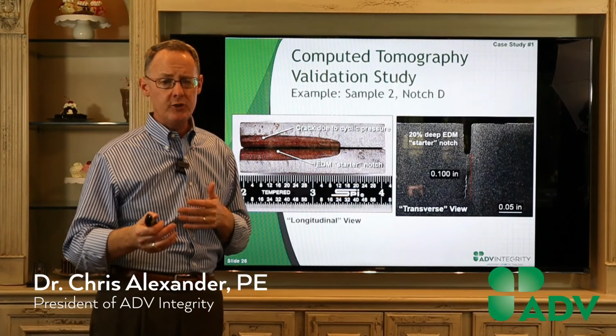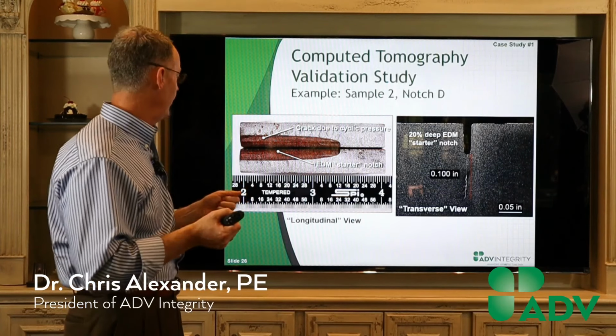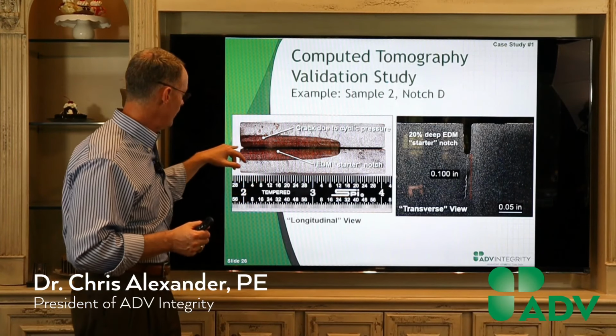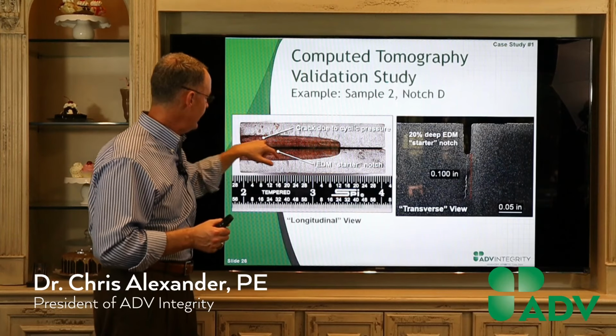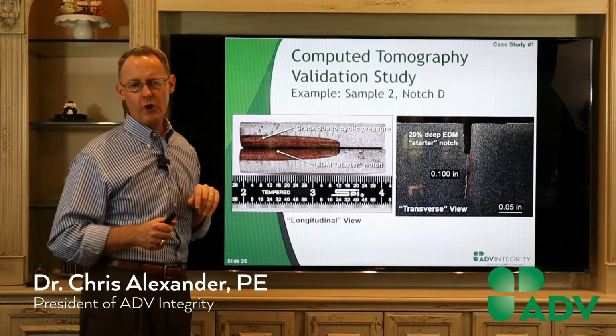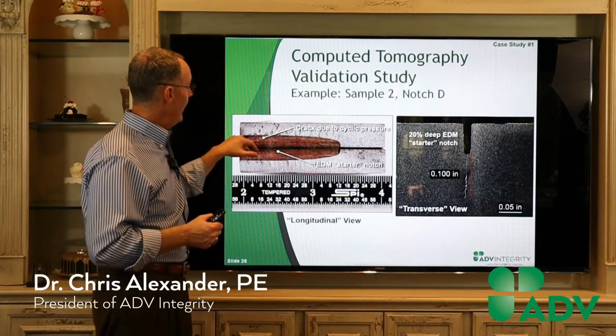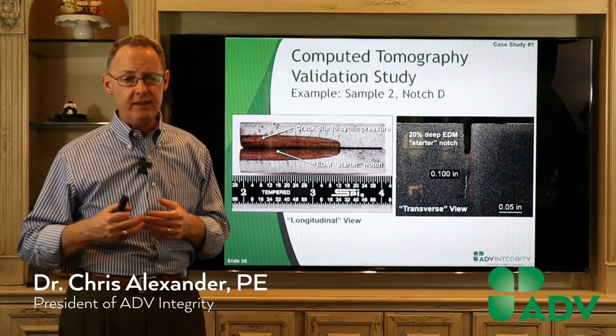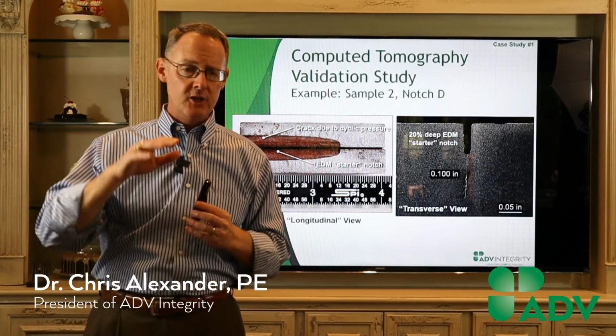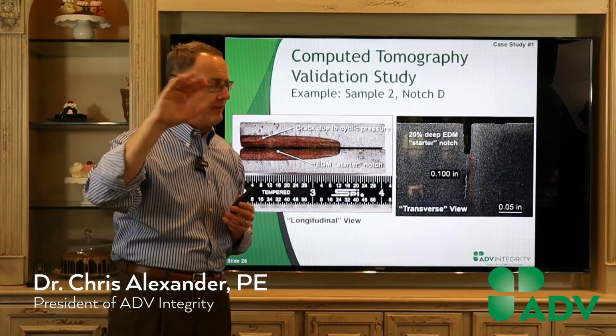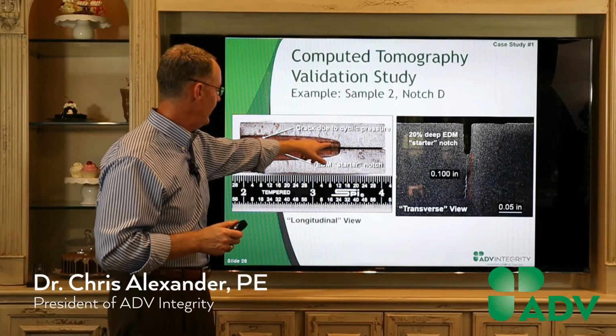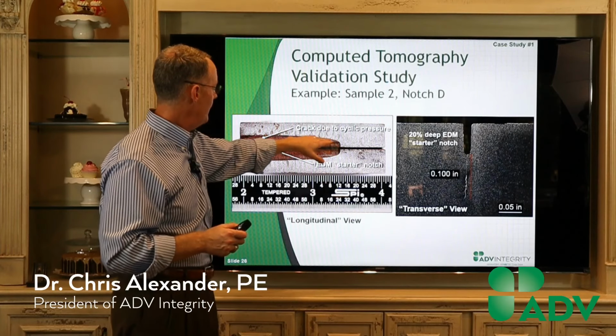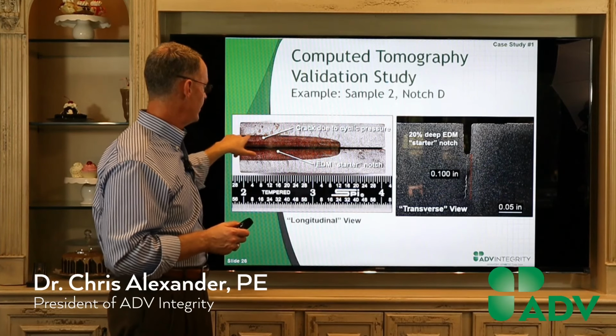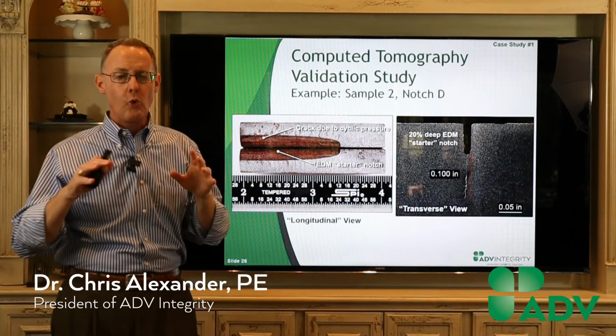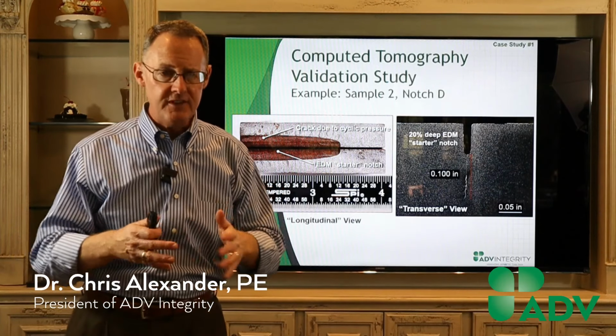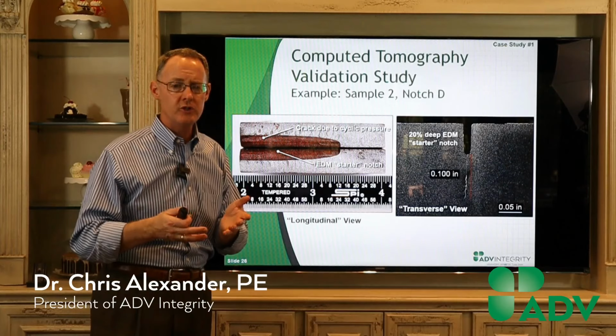So as I alluded to earlier, at some point we broke them open. And I'm not sure if you can see it on your computer screen, but there basically was an EDM notch, and we call this the starter notch, and then we cycled. If you've done any work in fatigue, the typical pattern that you get is an elliptical shape that develops. And so that's exactly what we see here. The EDM notch was flat bottom, but once we start cycling, you see the growth of the fatigue. And so you've got this notch that turns into a crack.